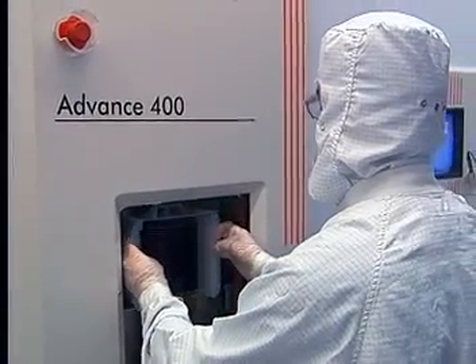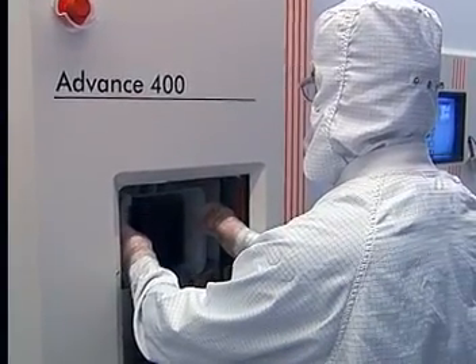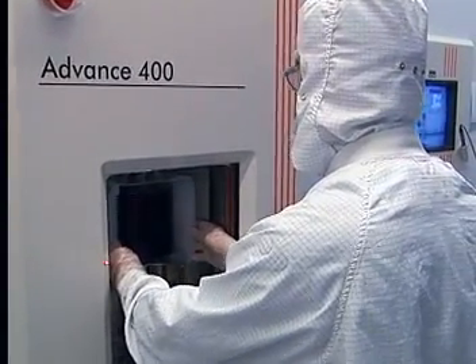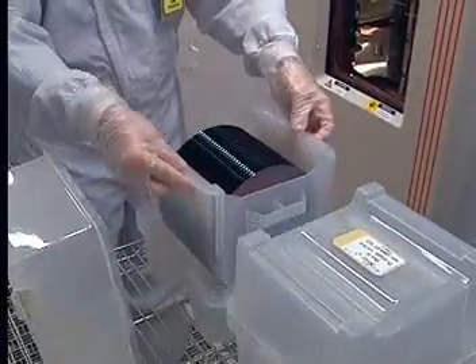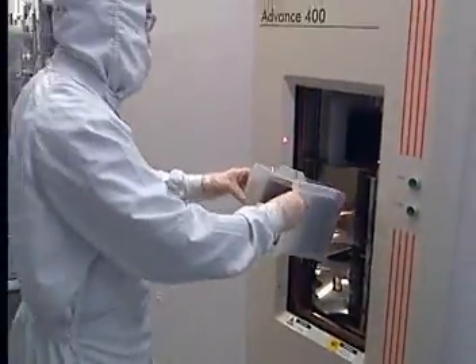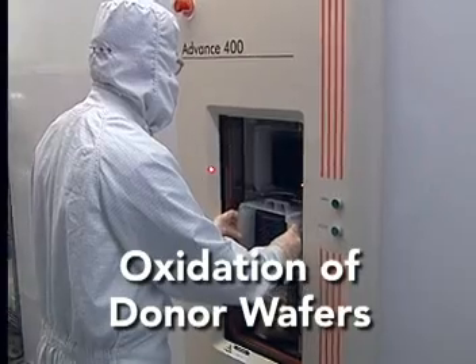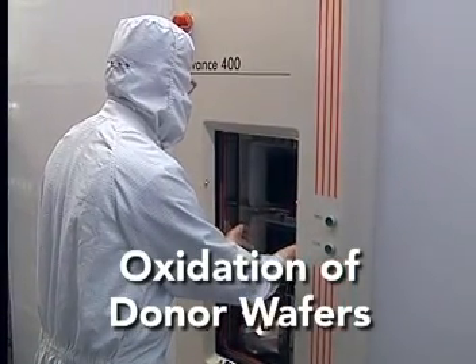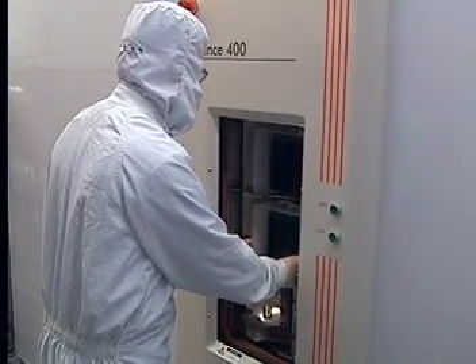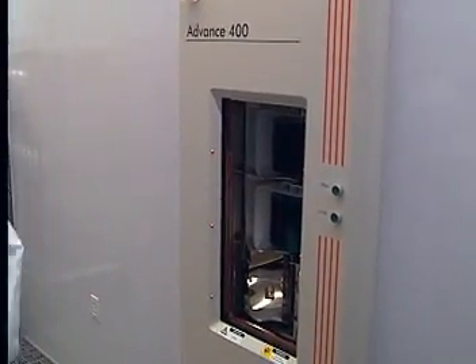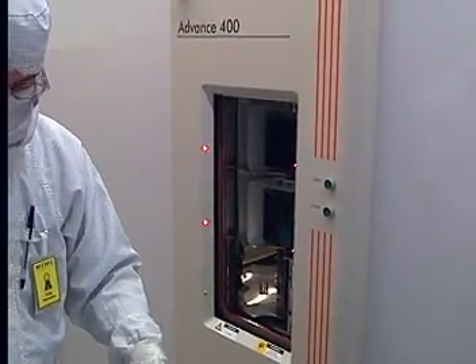MEMC's bonded SOI production process begins with the preparation of the donor wafers. In the first step of this process, the donor wafers are oxidized in a vertical furnace. This thermal oxide layer will ultimately form the buried oxide, or BOX layer, of the finished SOI wafer.